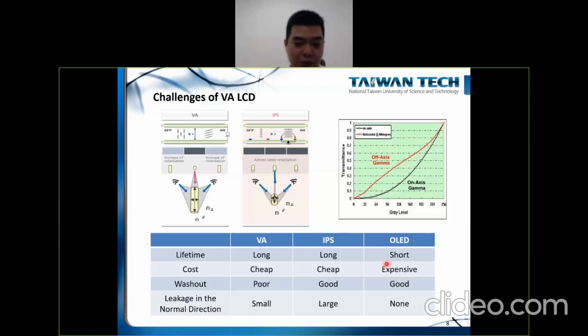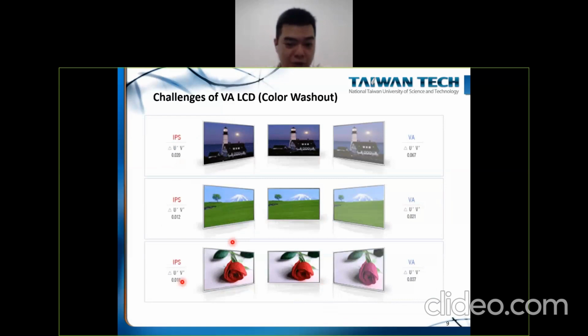the lifetime will be longer for the traditional LCD. Okay, and the cost will be lower, because the manufacturing yield for this traditional LCD is higher than the OLED. Okay, but you can see that VA experiences a serious color washout problem. And IPS and OLED have a better angular viewing quality for all-angle viewing experience. But for the leakage in the normal direction, IPS is not good because it always experiences some light leakage due to the orientation of the liquid crystal. So this is why, if you compare IPS with VA, you can see that the VA display always shows some light leakage problem at high angle.